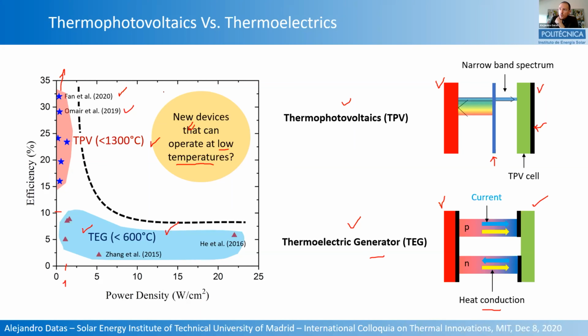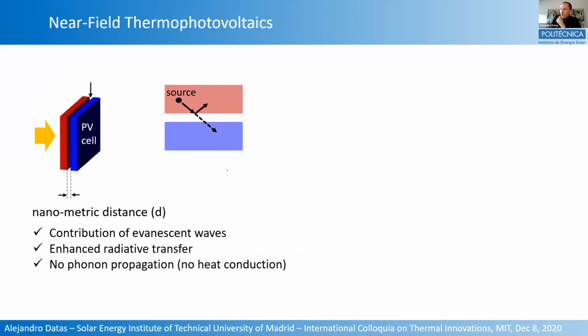Because obviously you can reach this region if we operate the TPV cells or the thermionic converters at extreme temperatures. For instance, if we go to 2000 degrees Celsius, we can operate in this region. But we want to do it with low temperature heat sources where most of the applications exist. And this is what my talk is going to be about. There is a concept that has a potential for approaching this region of high power density and high efficiency, and this is near field thermophotovoltaics.